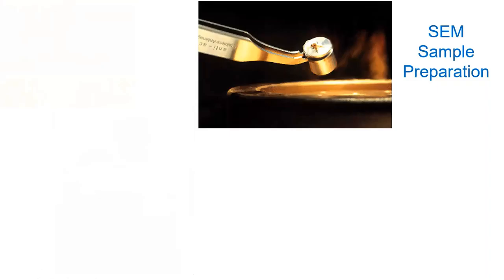Here's the sample preparation for SEM. The sample — in this case a mosquito held by forceps — is put into a sputter coater. You stick your sample in, press the button, and two minutes later it's coated with a very thin layer of gold. Gold is a heavy metal with lots of electrons, and if you want to see things with electron microscopy, having electron-dense samples is good. Gold is common for SEM — it's cheaper than platinum and works really well.